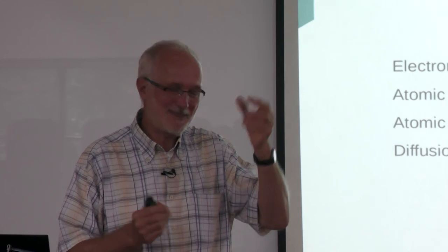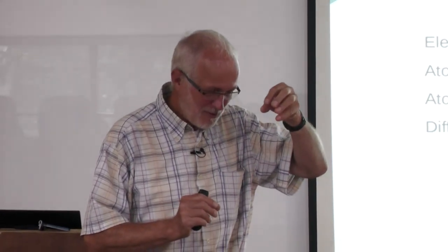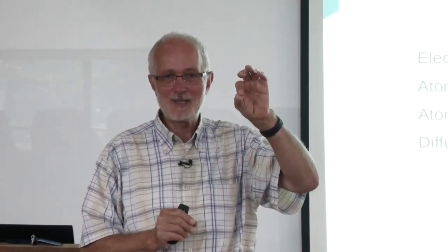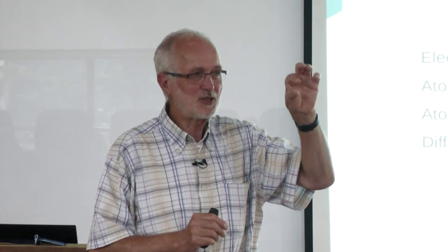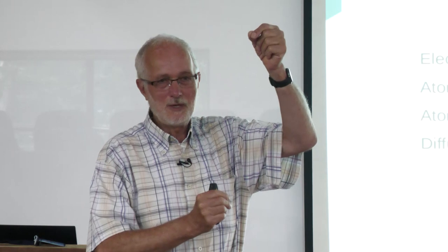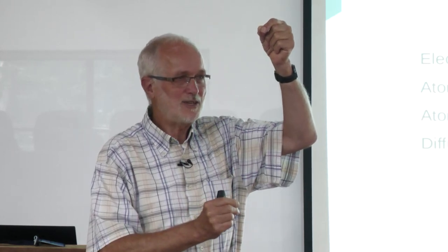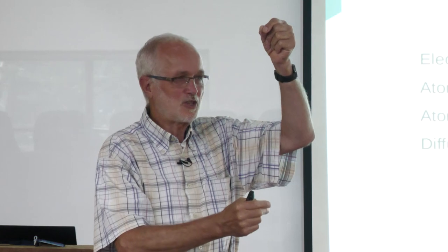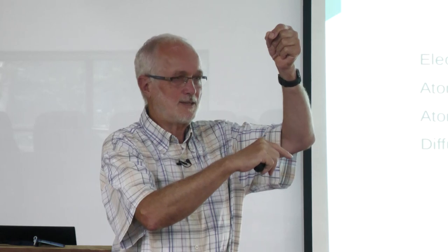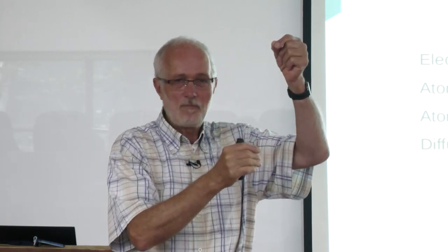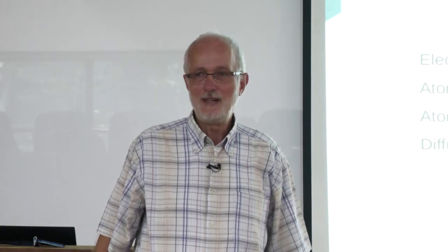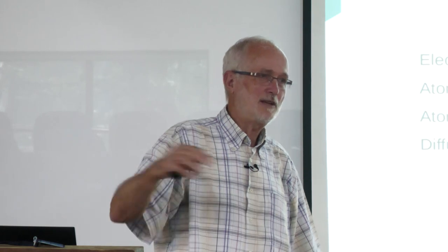It's a relaxation, or I guess you know that carbon sits on interstitial sites, octahedral interstitial sites in BCC iron, in alpha iron. And then if you pull the crystal in one direction, these interstitial sites become non-equivalent. Yeah? So the atoms jump into particular sites. Yeah? And this can be measured. And from this, you can determine the jump rate of the carbon atoms in the solid.